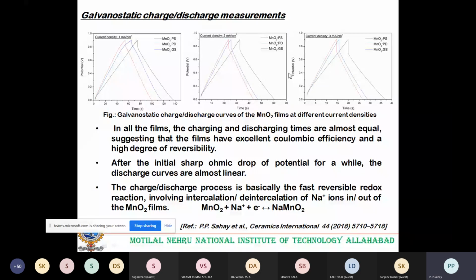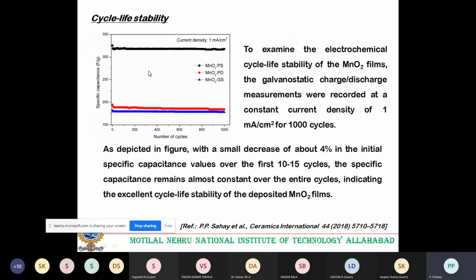And we calculated the specific capacitance, and we see that the specific capacitance is almost constant with a small decrease of about 4% in the initial specific capacitance values over the first 10-15 cycles. The specific capacitance remains almost constant over the entire cycle, indicating the excellent cycle life stability of the deposited MnO2 films. So the deposited MnO2 film exhibits very good electrochemical stability.